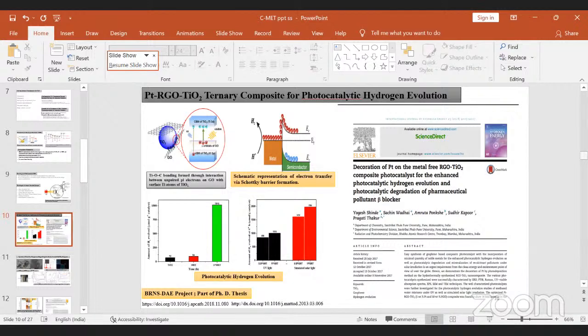Okay, so here I would like to share the result of platinum-RGO-TiO2 ternary composite for photocatalytic hydrogen evolution. We all know that platinum is the best co-catalyst for photocatalytic hydrogen evolution because of its very high work function, and it is a good electron sink. It creates a Schottky barrier when you decorate platinum with TiO2, so the platinum takes away the electrons, and the electrons are used for the reduction of H+ to H2. But the thing which is not favorable here is that platinum is a noble metal and it's very costly.